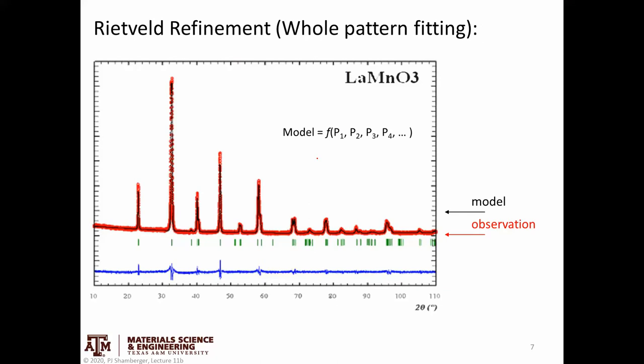Very generally: we have a number of observations. Each individual intensity point — measured as a function of scattering angle — counts as an observation. You can think of this as a very complicated function of a whole bunch of different parameters, due in part to your diffractometer and in part to the material itself. What we'd like to generate is some model function — the black line — that fits those observations as closely as possible. We look at the difference between these two to assess how good a job we're doing at recreating the observations with our model.